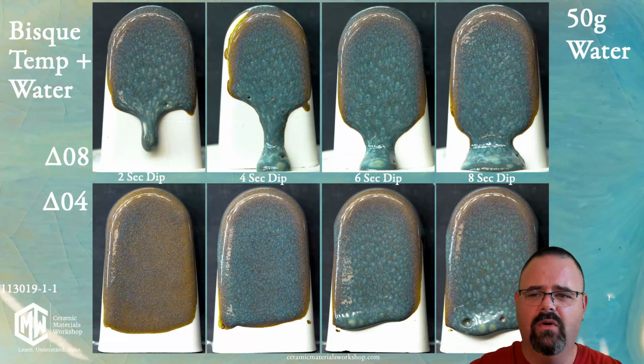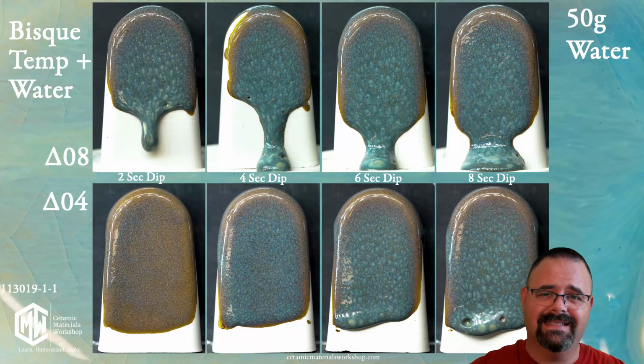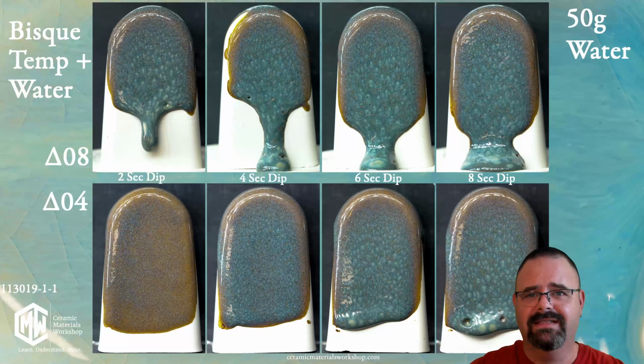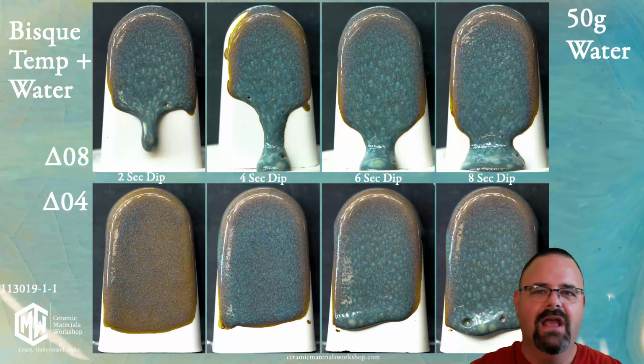So in this case, we can see at cone 08, we got a very thick coating, but at cone 04, suddenly the 2-second dip doesn't have that same effect. In fact, it's not until we get to the 8-second dip where the glaze begins to look the same. Well, that is because there is lower absorption in my clay at cone 04. Now, once the glaze gets thick enough with the 8-second dip, the glaze starts to look the same as the 2-second dip at 08. But this is why having a consistent bisque temperature is so important. If you bisque to cone 08 one day and cone 06 the next day and cone 04 the day after that, your application qualities are going to be completely and utterly different. You need to stay consistent.